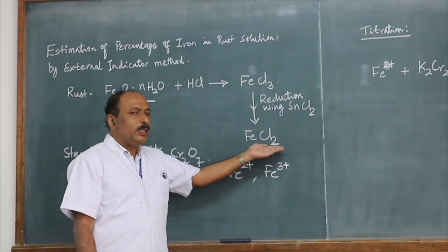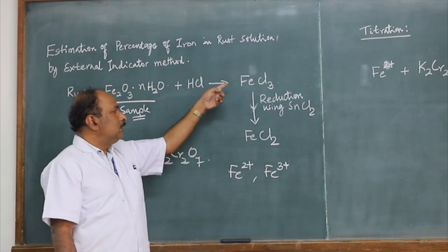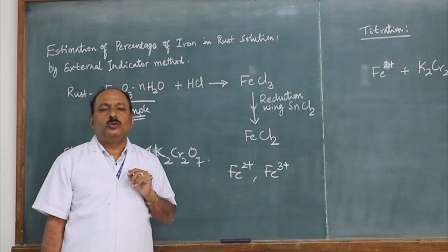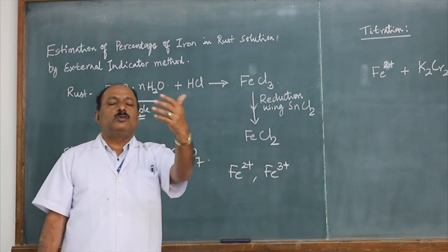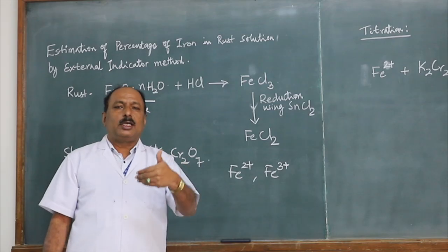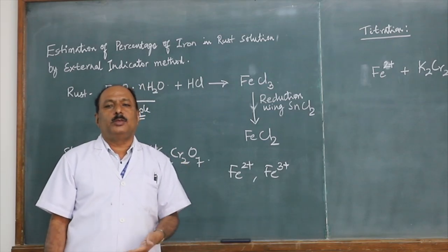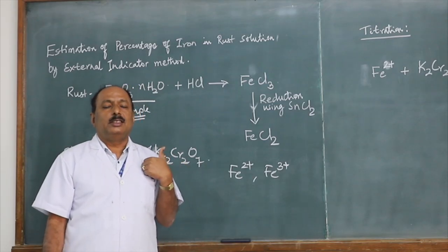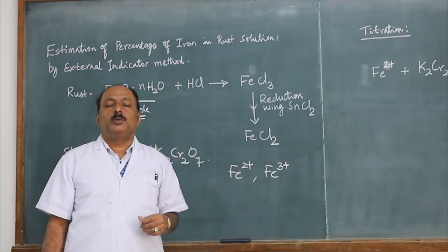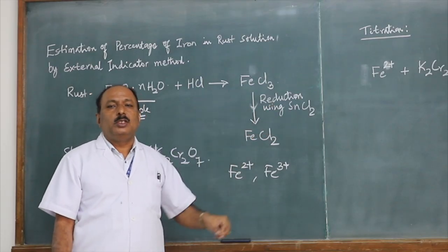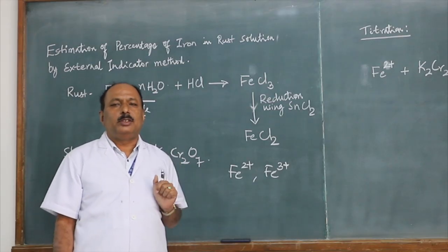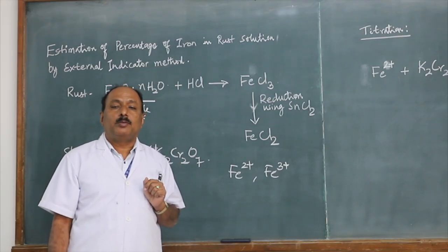The black precipitate forms because this reaction is sensitive to temperature and the concentration of stannous chloride. If the residual concentration of stannous chloride is high, there is a chance that instead of a silky white precipitate, you will get a black precipitate. And if the temperature of the solution is not proper, at room temperature, there is also a chance of getting a black precipitate.